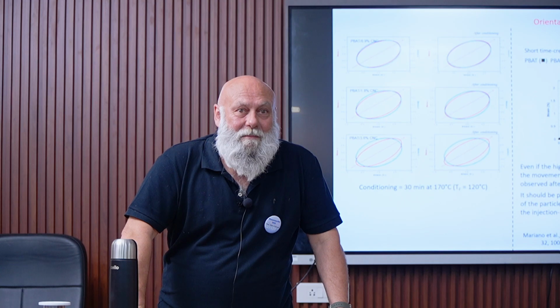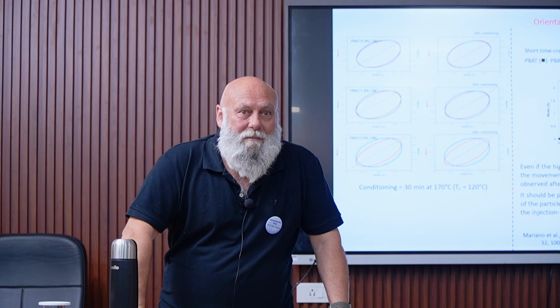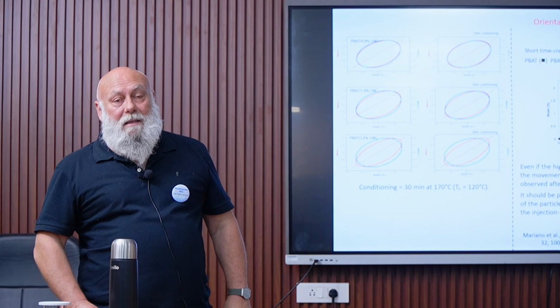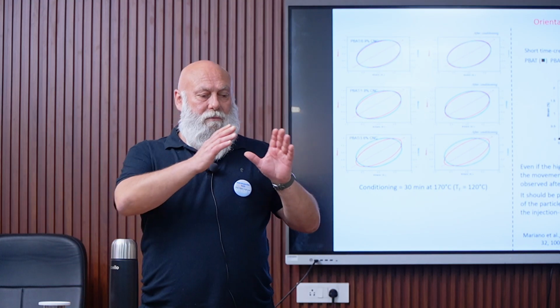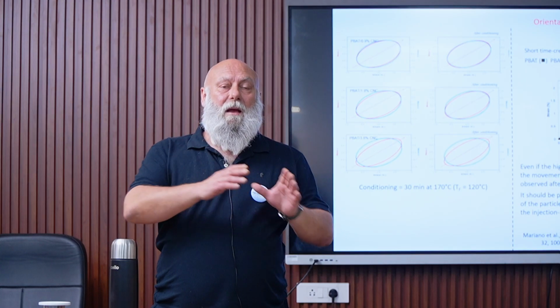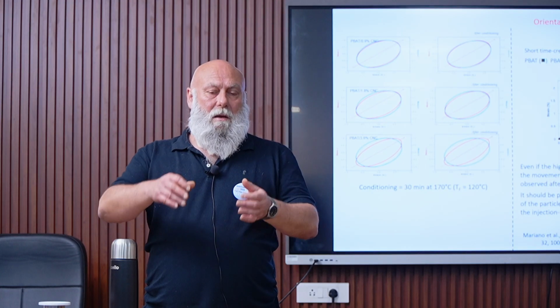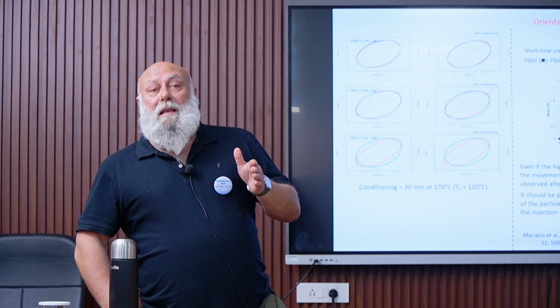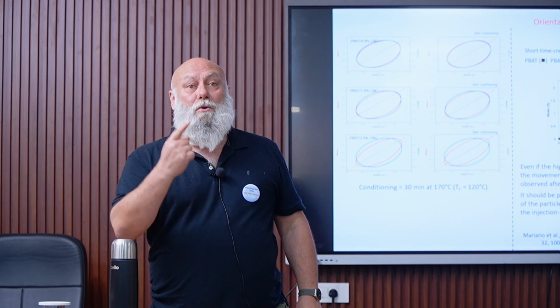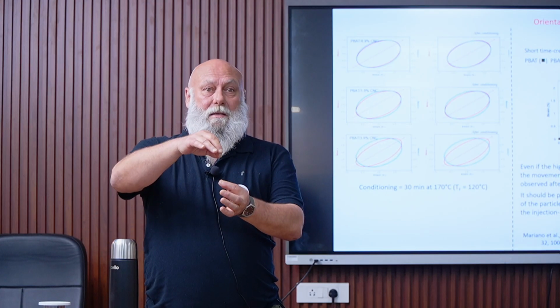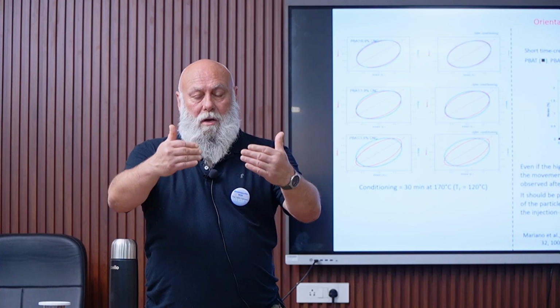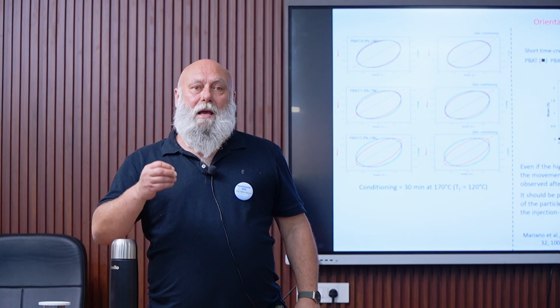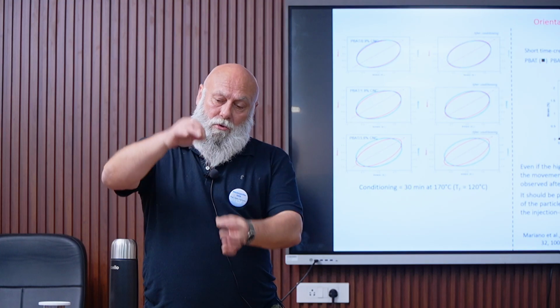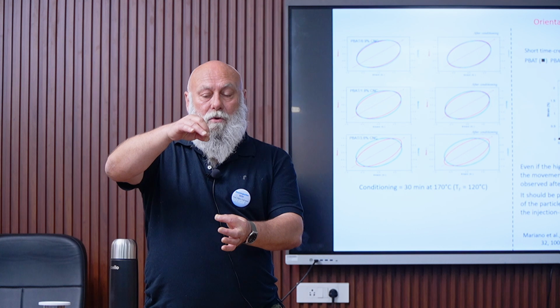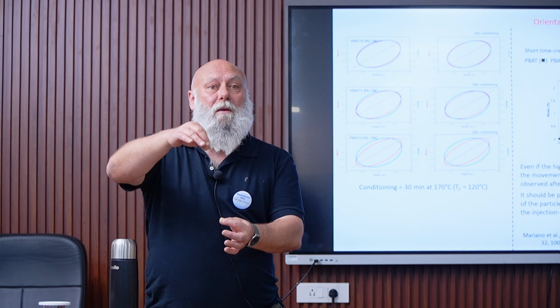I'm feeling it should be around 50% of the melting point. Then it is almost the same as a tensile test at high temperature. No, it's not a tensile test. In fact, for mechanical tests you have two different types: static tests and dynamic tests. Dynamic test is dynamic mechanical analysis, meaning that a sinusoidal stress is applied. Static test means that one mechanical parameter is constant. In the case of creep, it's stress. A constant stress is applied to the material and you can follow the evolution of the deformation. Stress relaxation is a test in which the deformation is constant, so you stretch the material, for example, and you keep the deformation, and you follow the evolution of the stress which is necessary to keep this deformation as a function of time. Tensile test is also a static test.